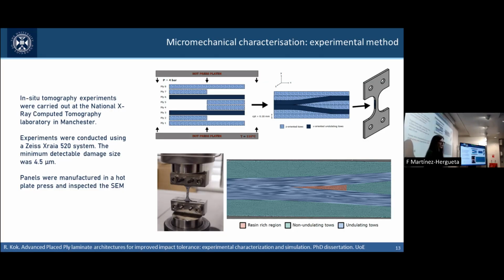For the micromechanical characterization, we directly focus on the response of these undulations that are repeated over these AP-PLY composites. We manufacture a laminate that introduced one of these undulations, and we can observe that there are 3 different sections. I'm pointing here now. Our tensile direction, our loading direction, was axial to this undulating tow. So that's the direction of testing. Then we also have non-undulating tows that are perpendicular, and we always have a resin-rich region that originates somewhere near here through the resin flow.